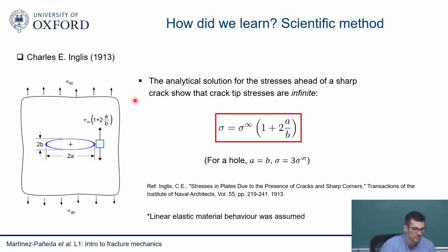It was all analytical. So he says, for a remote applied stress of sigma infinity, I'm going to predict what the stresses will be at the tip of this ellipse. And he figured out that this was the solution, and this solution was mathematically rigorous but puzzling to many scientists and engineers back then, because they said, well, we learned a few things here. First of all, if you have a perfect circle, A equals B, then the stresses at the tip of your circle are going to be 3 times the applied stress, and this is something that mechanical engineers know by heart. You always get a stress that is 3 times as large.